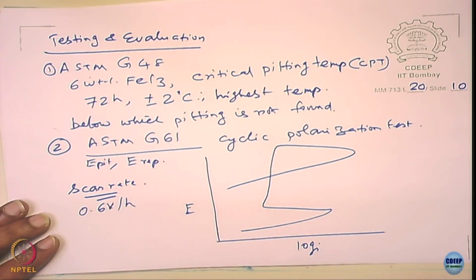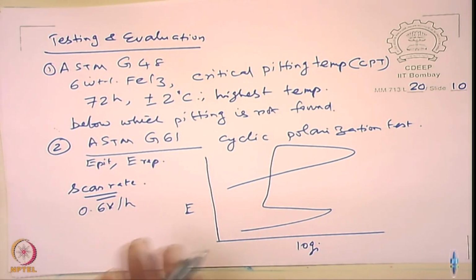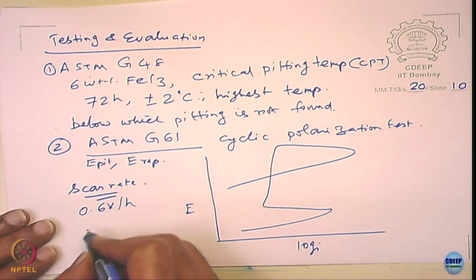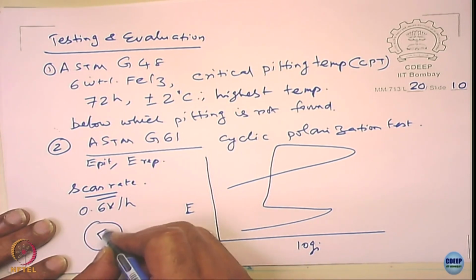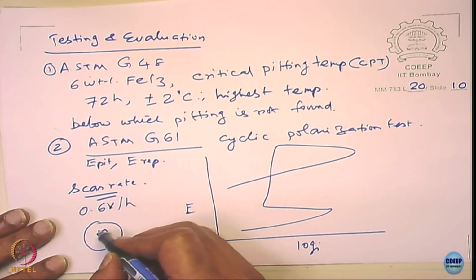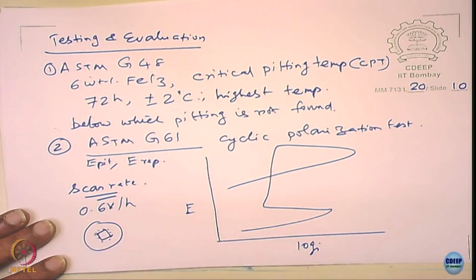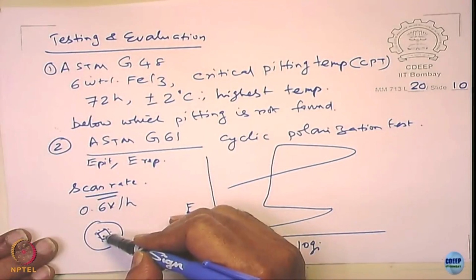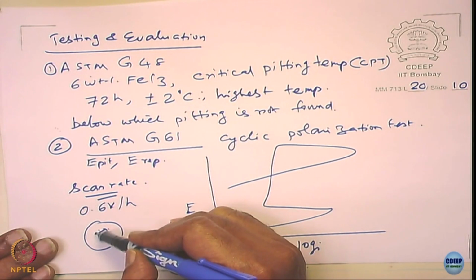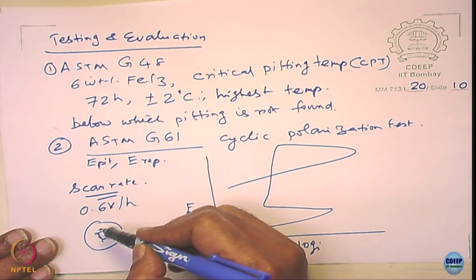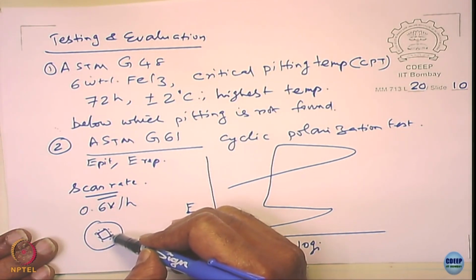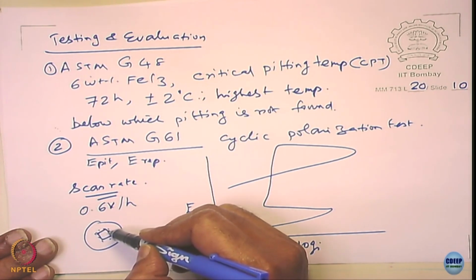There are some problems you normally encounter. If you do 0.6 volt per hour, sometimes you will get a crevice attack in the samples. You know, sample sometimes you mount it, no? You have a mount here, you keep the sample, and you may get a crevice attack. You must ensure that there is no crevice attack taking place. If there is a crevice attack, then E pit will be lower than the actual value. Why? Before pit occurs, the attack takes place along the interface here. So mounting the sample properly, ensuring that no attack occurs at the interface between the sample and the mount is a very important thing.